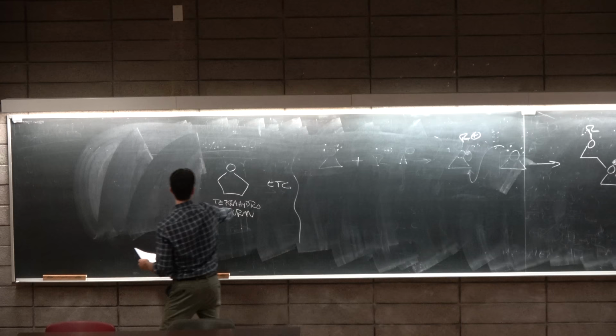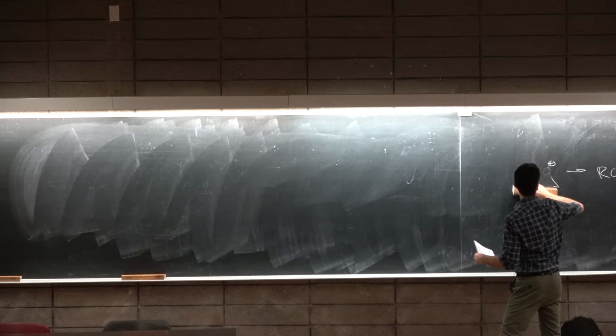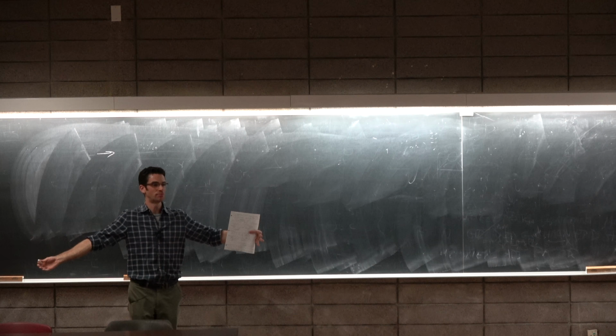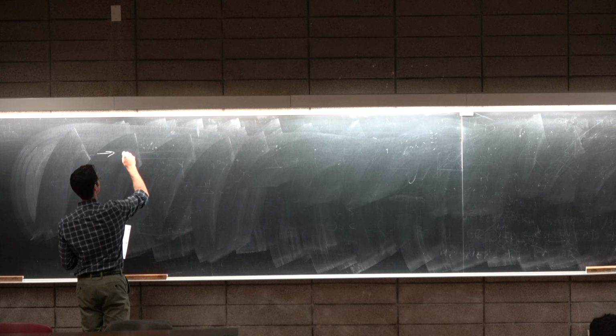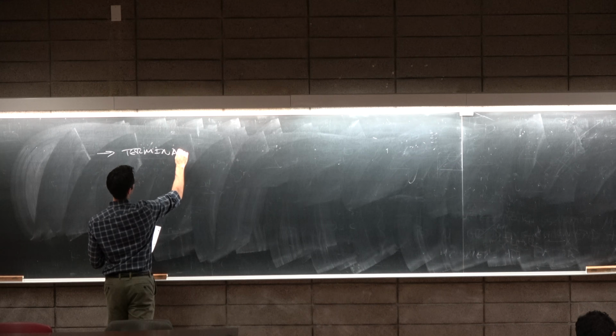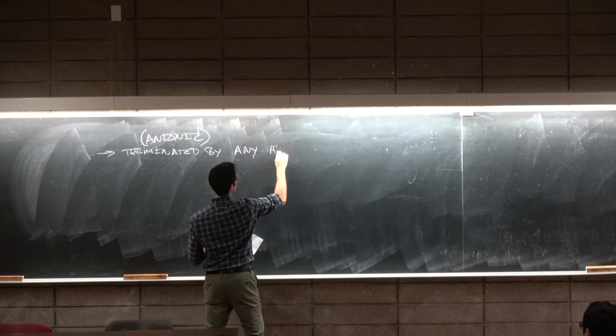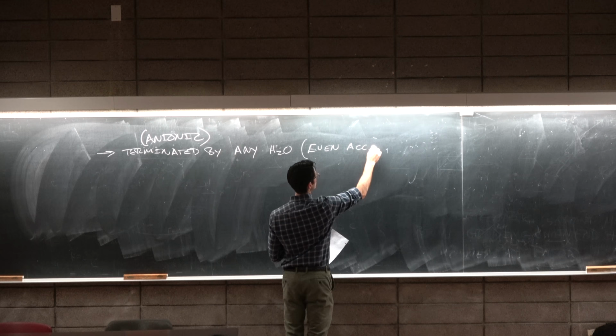Okay, back to anionic. Your reactor or reaction flask must be assiduously dry, so no water on the sidewalls at all. This is anionic again. Terminated by any H2O, even accidental.